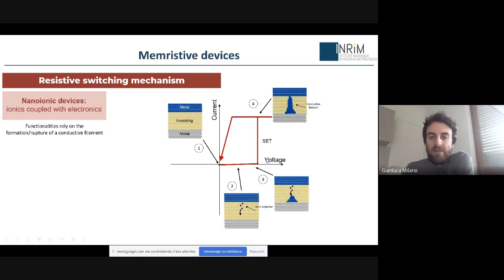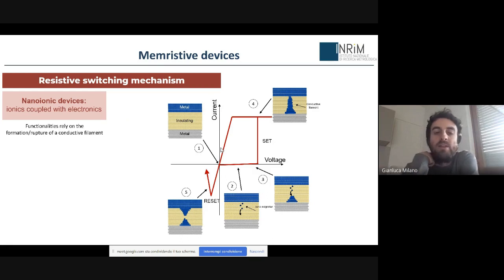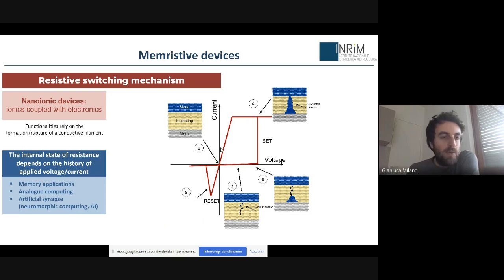At a certain point, we have the formation of a complete channel that is connecting the two metal electrodes, and then a filament is formed. And so we are changing from a low slope in the IV plane to a high slope that is associated to a low resistance state. And this process is reversible, meaning that if we apply an opposite voltage, we can retract these atoms and we can reset our device. And so we can achieve the complete hysteretic loop that is the typical fingerprint of memristive devices. Basically, these are devices where the internal state of resistance depends on the history of applied voltage and current. And for this reason, these are promising for memory applications as well as for analog computing and for the emulation of artificial synapses in the field of neuromorphic computing and artificial intelligence in general.